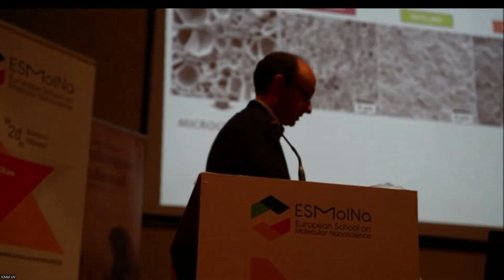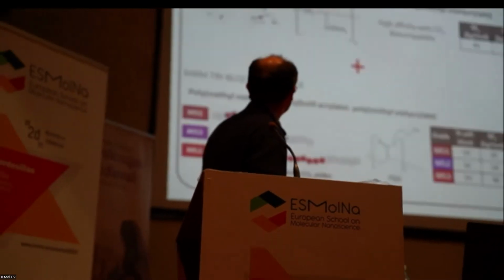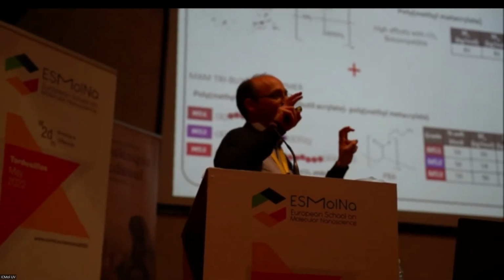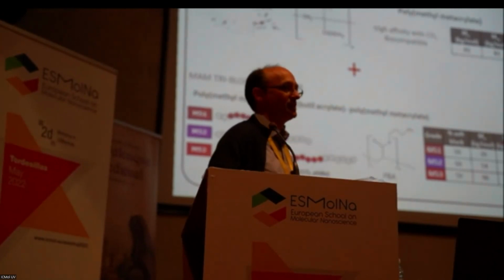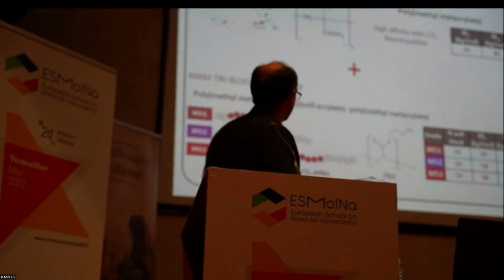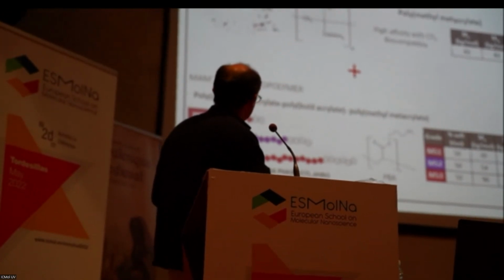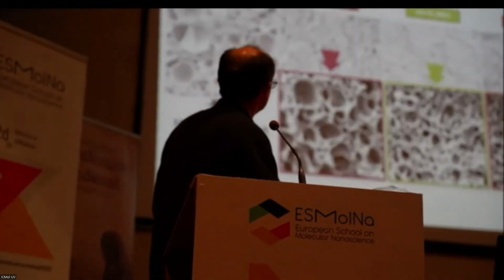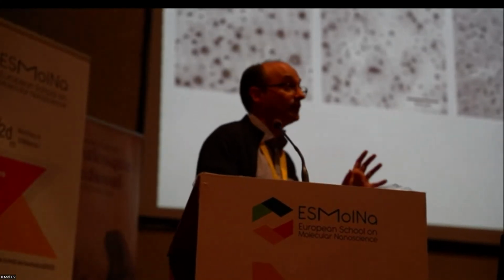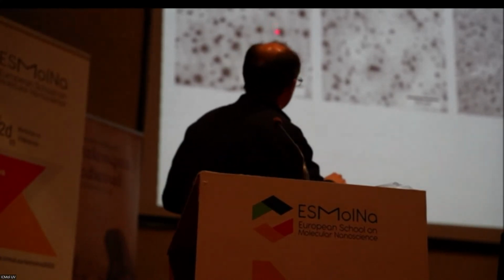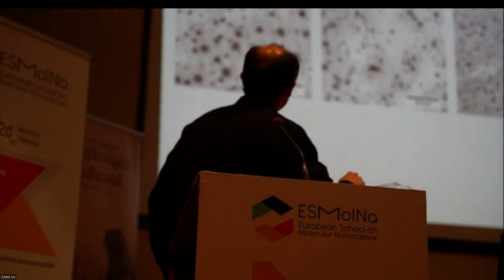Yeah, in fact, for instance, in this example, we are mixing polymers. This is a blending of polymers. For instance, here we have a polymer, PMMA. PMMA is our, let's say, model system because it has high solubility and a very low glass transition temperature. So it's very nice to work with. And in this case, we are combining this polymethyl methacrylate with copolymers in which we have 3 blocks: methyl methacrylate, butyl acrylate, and methyl methacrylate. So when you do this, basically the PBA phase organizes in nanometric micelles. And as the solubility of CO2 in PBA is even larger than in PMMA, most of the gas is dissolved in this area and the cells are created in this area.